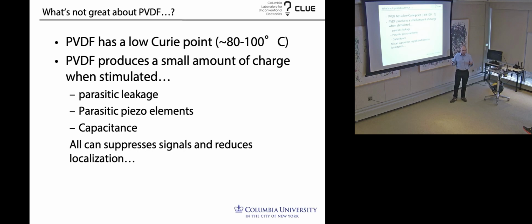I mean, why don't we use it for everything? And why do we always joke it's the material of the future? Well, it has a number of weaknesses. And one of the biggest weaknesses is that crystalline form I mentioned before, in which we stretch it and set it up so that the fluorines point one way and the hydrogens point the other. It turns out that that is not the thermodynamically stable phase of PVDF. Unfortunately, the thermodynamically stable phase is paraelectric, where the fluorines and the hydrogens are not preferentially oriented in one direction.